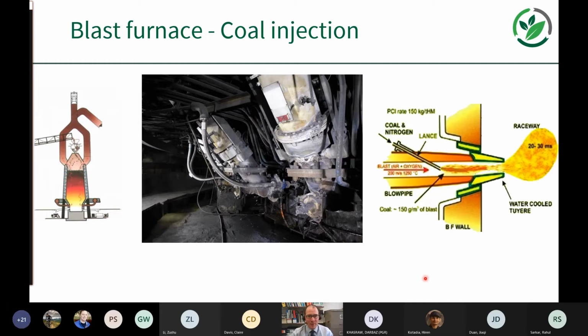So the picture in the center shows the pipes coming down, which are the hot blast, the heated air that's directed into the bottom of the furnace, and it's directed in through these nozzles, which are located around the bottom of the Bosh area of the furnace. That's called the bustle main, and that directs hot blast into the bottom of the furnace. And then you've got these braided metal flexes where coal is injected into the bottom of the furnace. And then on the right-hand side, we've got this cross section of this coal lance, directing coal into the hot blast, and that tends to form a balloon-like void known as the raceway.